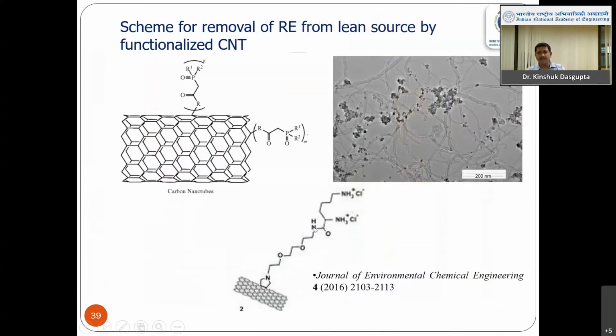So we get some scheme for that, means how it helps. Even the ligands, which are very much specific to the rare earths, get functionalized with the carbon nanotube, and then this can attract the particular ion, which is here the rare earth ion. Here I am showing a transmission electron microscope image where we took the NdFeB, that is neodymium iron boron magnet, scrap, and we made it into solution, and from there specifically Nd got attracted on the carbon nanotube, which is functionalized with the ligands which are specific to Nd.